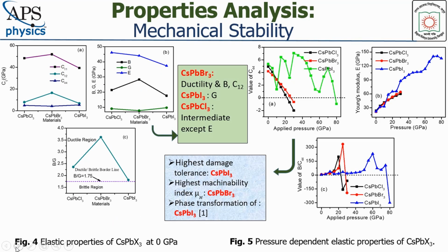Now let's have a look at the pressure independent and dependent mechanical properties. All the mechanical properties are calculated implicitly and explicitly by these three elastic tensors C11, C12, C44 shown in figure 4a. Mechanical stabilities are confirmed by Born criteria.